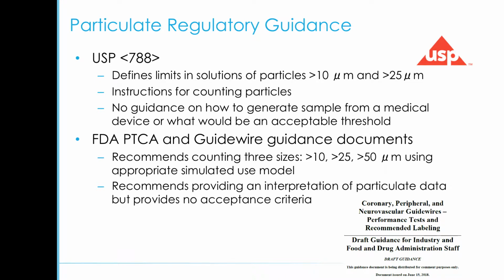The challenge is there are standards and guidances for coatings, but none are really entirely applicable for evaluating particulates from medical devices. Now, there are particulate guidances from agencies such as the United States Pharmacopoeia. There's one on particulates for injectable solutions, USP 788. This defines limits in solutions, so a vial that is being injected. And they recommend totaling up particles that are greater than 10 microns as well as particles that are greater than 25 microns.